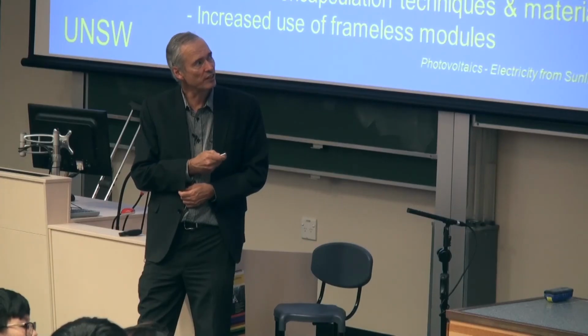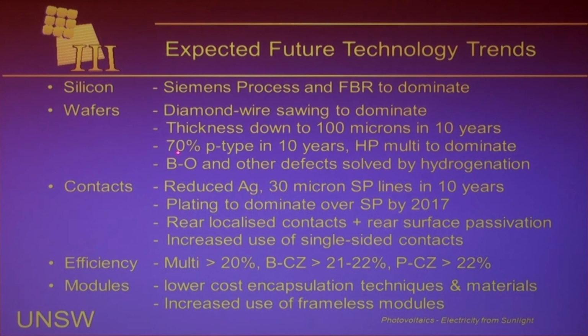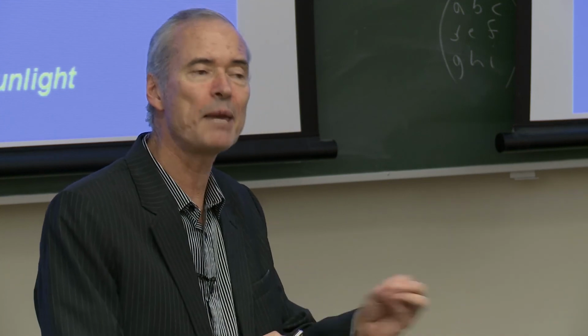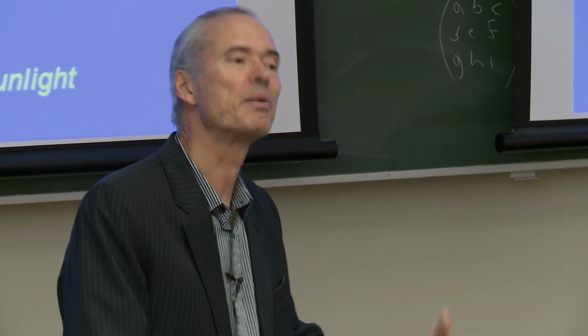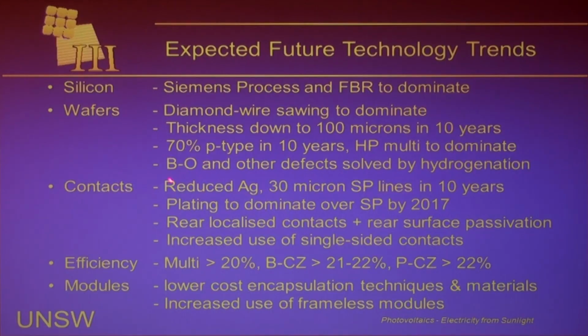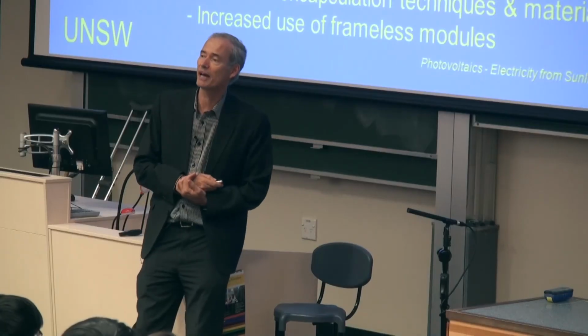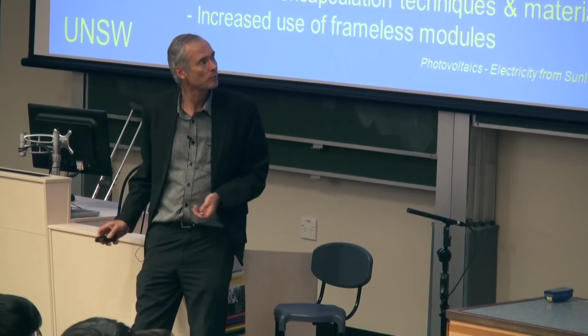Also, we see this evolution in the type of silicon. 70% in 10 years' time is still expected to be P-type silicon. There's been a lot of discussion on this because N-type silicon is usually considered capable of making higher efficiency solar cells, but it's more expensive to do so. So the expectation is that within 10 years, P-type silicon will still dominate, probably about 70% of the market. And this new type of process involving the high-performance multicrystalline silicon is what is expected to dominate. I'll talk a little bit more about that shortly.